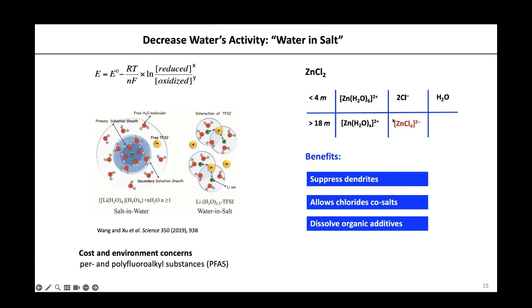With this anion, this is a very soft, bulky anion. It is our hypothesis that if you use a very soft, bulky anion, it's going to generate free water molecules. When you have free water molecules, it's going to dissolve hydrophobic molecules. I won't have a lot of time to talk about that, but for now you can see that I will show the evidence, and this helps dissolving organic molecules.